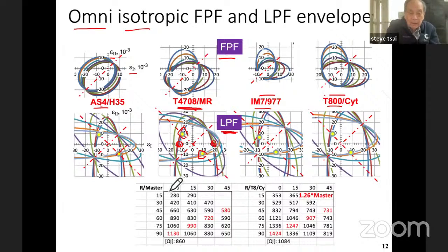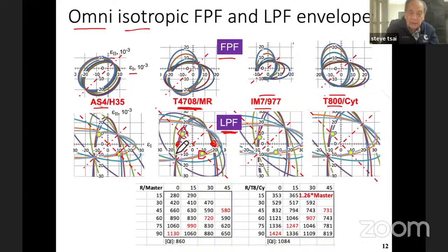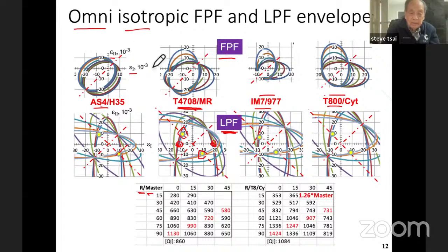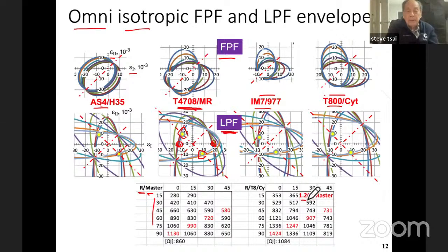Therefore, we find a radius — the area of the failure envelope — as a key parameter. The equivalent area of the failure envelope is replaced by a circle, and the diameter — we call it the R value — applies to various materials. It turns out there is a master material: you take all the omni-envelopes and take the average. For any specific material, you simply multiply by the particular scale parameter of that material, making it very simple.